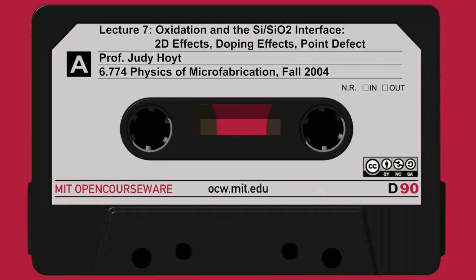So you can see these differences even if you're not doing shaped surfaces, just in planar surfaces. Now, we chose a very extreme example, 1100 degrees, which is quite hot, above the flow point of the glass, and 800, which is quite a bit different. Maybe you typically wouldn't do such a wide range, but it really does tell you that history effects can be important when you're trying to do accurate modeling. And in fact, most simulators don't take this into account. So it's something you'd have to account for either empirically in your process or calculate it yourself. But that's an interesting effect that goes beyond shape effects.